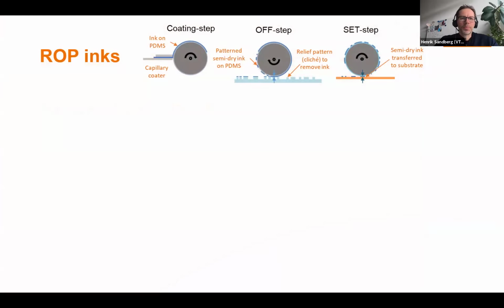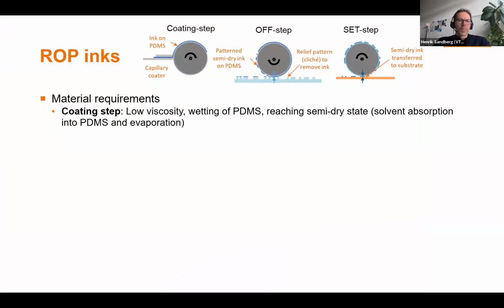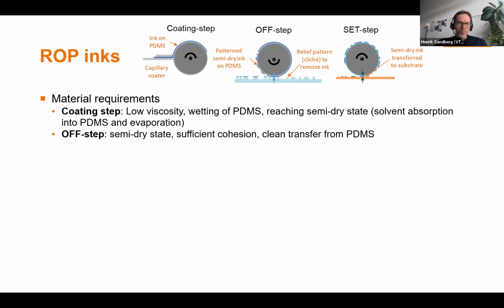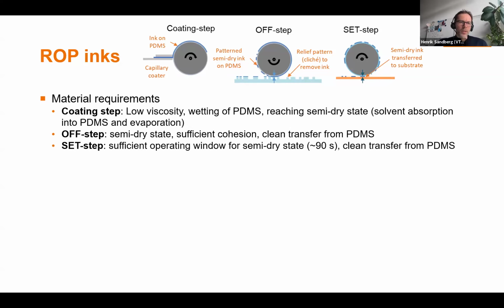What are the materials here? As mentioned, we have this PDMS, which we have to optimize and develop, and then the inks. And the viscosity must be low, and it has to have the optimal wetting properties on PDMS. It should reach this semi-dry state, and it has to maintain this state for a sufficient time. And the reason, it also has to have the sufficient cohesion to make the transfer from the PDMS as clean as possible, both onto the cliché and onto the substrate.